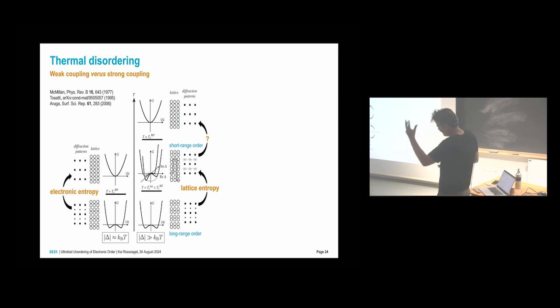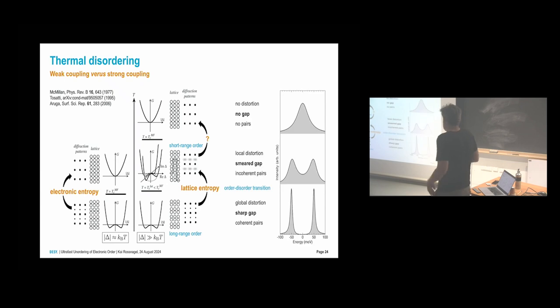If you do an optical excitation, we can always go above, excite electrons across the gap. So this is in a sense not critical. We are always above. So we will have electronic and lattice entropy in these types of mechanisms. And then I'm interested in the electronic structure change, because again we want to use it as a switch, or could use it as a switch, and then we should look at the gap, which is then the measure of